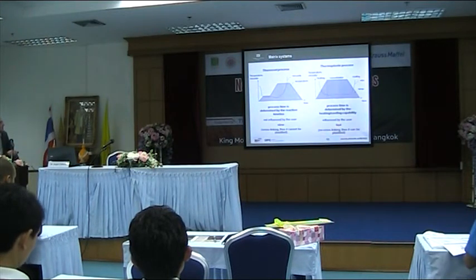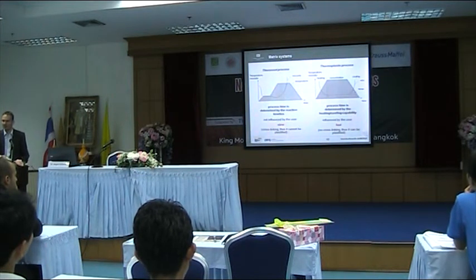Okay, so something about the fibers now, getting the insight why we are focusing on thermoplastic processes. I think this is something typical when looking at thermoset processes: the processing time over the viscosity and temperature for producing the parts. So when we look at a typical thermoset process, for example resin transfer molding, some liquid composite molding, you have a viscosity of the thermoset resin, you mix it, and curing starts. In the first reaction time, the viscosity goes down. This is what you use for impregnating the textile preform with matrix. The viscosity is really low.